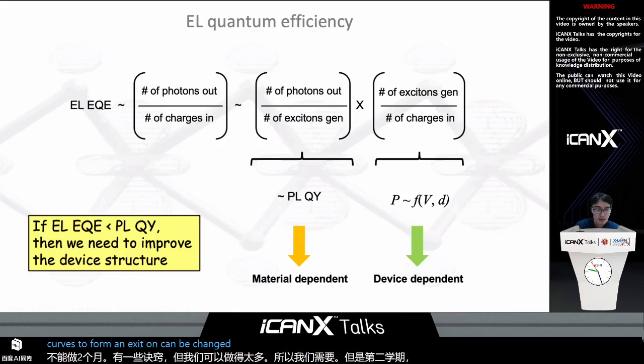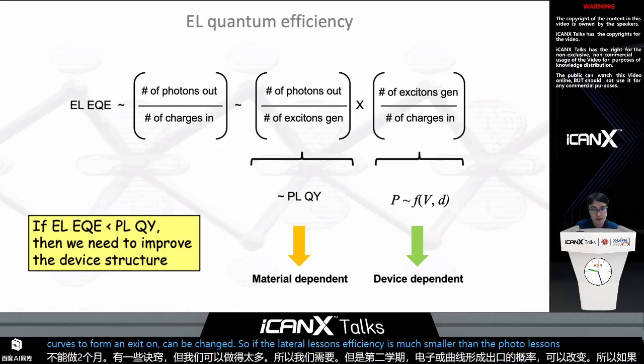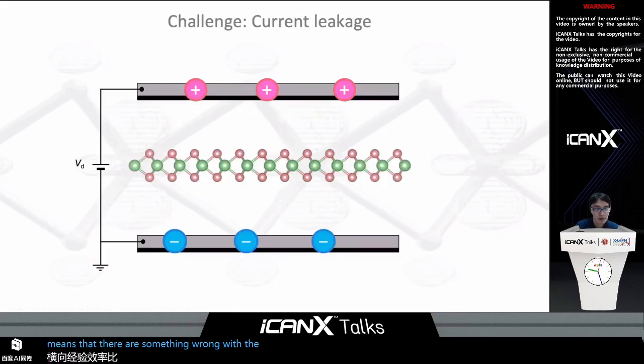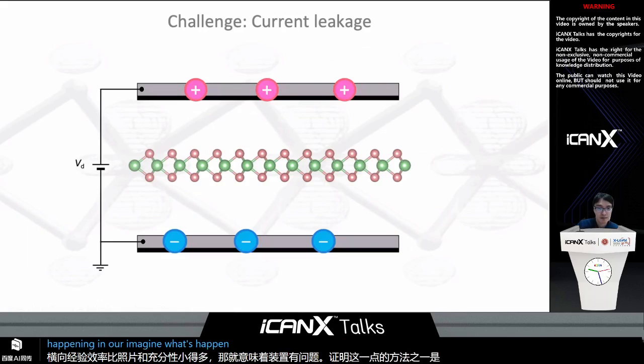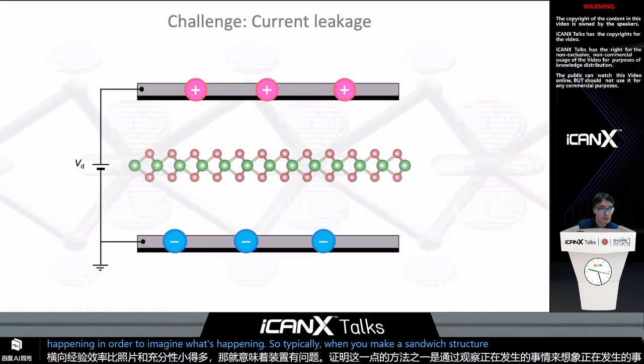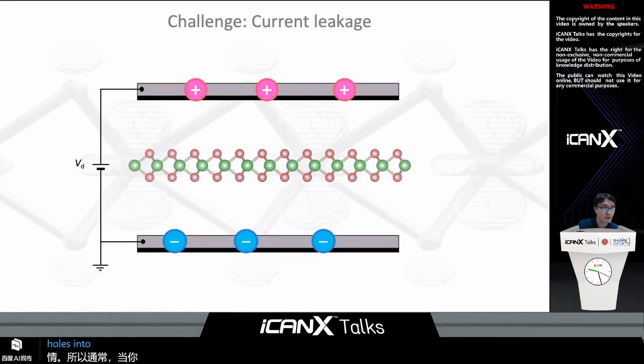So if the electroluminescence efficiency is much smaller than the photoluminescence efficiency, that means that there is something wrong with the device. And one of the ways to demonstrate this point is by looking at what is happening. So typically, when you make a sandwich structure, we inject both electrons and holes into the 2D material and hope that they form electron hole pairs or excitons.